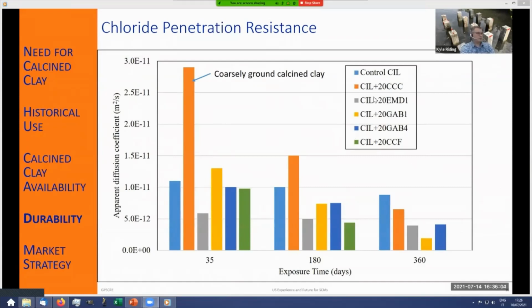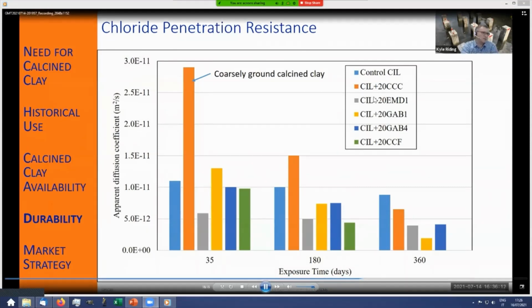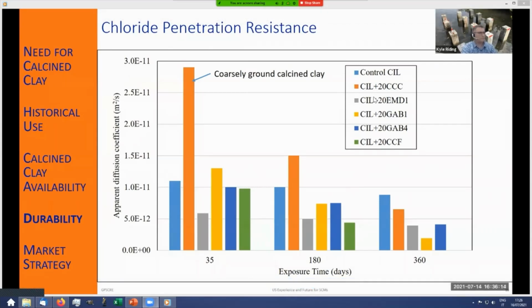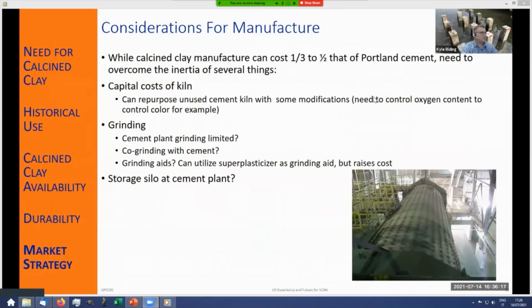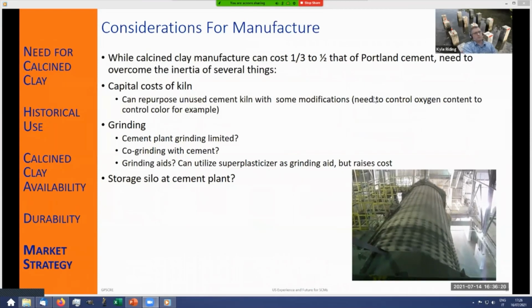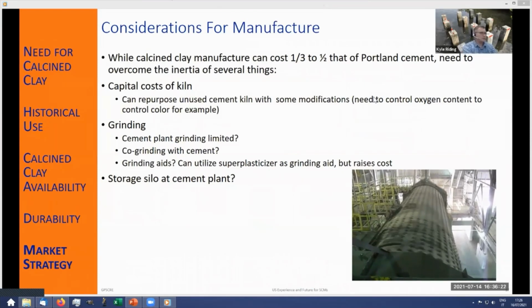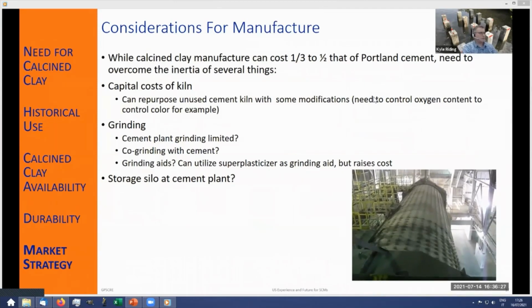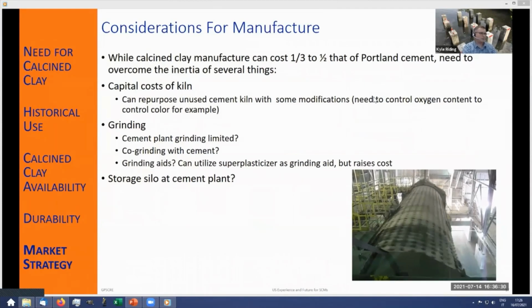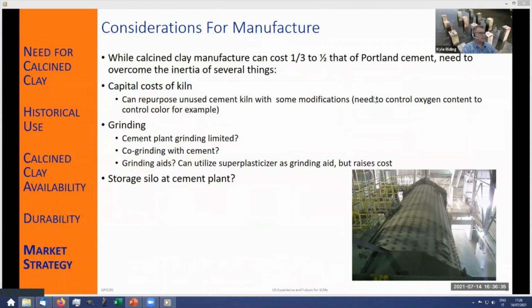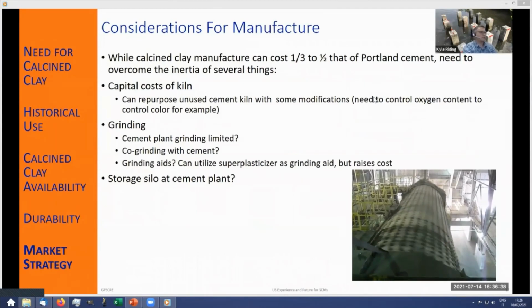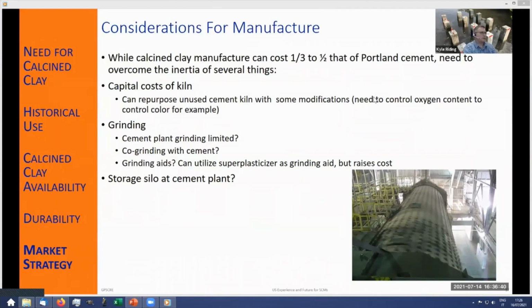But you do have to control your process, and if you control your grinding and your quality control of your materials, then you're going to make sure that you get that performance from day one. When we look at this material, we've seen that it is very durable and it can give you good strengths. The question then is, can you manufacture it economically? So we have a material with calcined clay, especially when used in conjunction with finely ground limestone, whose performance is great, but can we manufacture it economically?